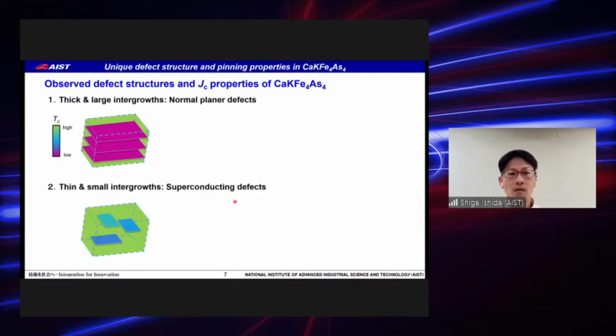Let me discuss how these defects correlate with JC properties. As we observe, there are two types of defects in calcium potassium 1144 single crystal. One is thick and large intergrowths, which are considered to be normal planar defects. These defects are in general very efficient pinning centers for magnetic field parallel to this plane, so in this case, the AB plane. On the other hand, they are not efficient for the field perpendicular to the plane, namely along the C-axis.